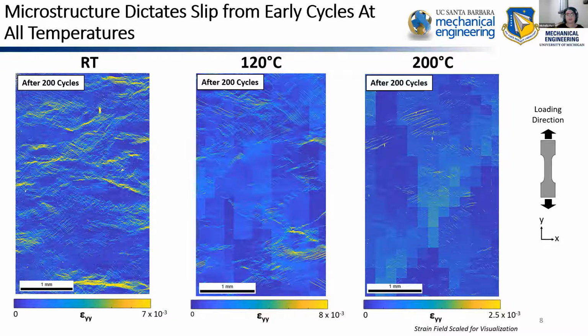Yes, sorry. In this particular presentation, since it was limited in time, I chose to focus on the microtextured regions. And since I ran my experiments at temperature, I also needed to show the temperature effect. One of the theories is that at 200 C, you would expect to see significant strain everywhere, and we don't see that. Relating back to the bell curve, we're thinking that the mechanism doesn't fundamentally change from 120 C to 200 C. It has a lot to do with the fact that if you're heating it, your overall yield strength is going to drop significantly.